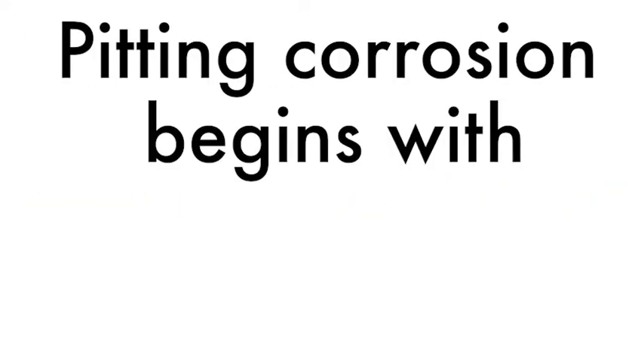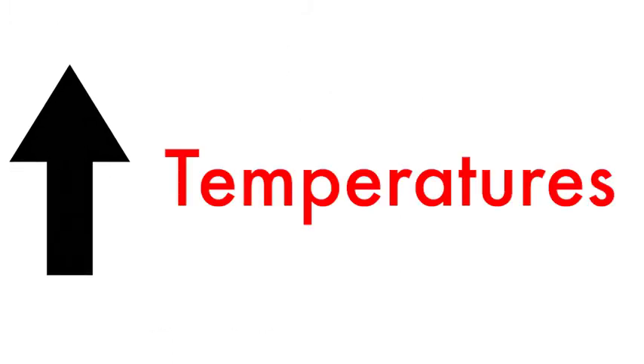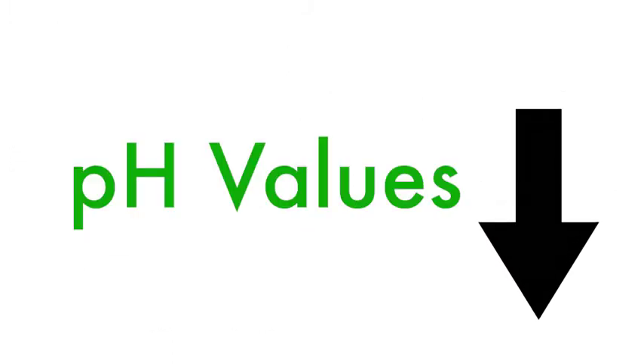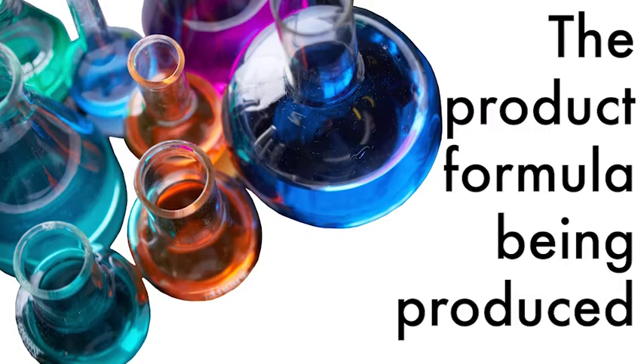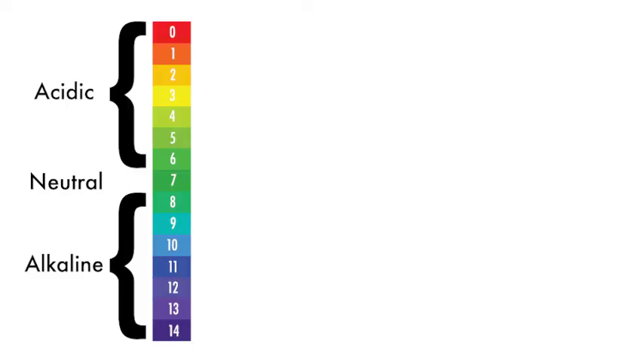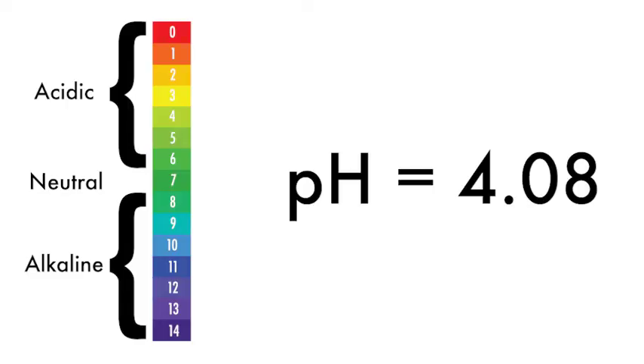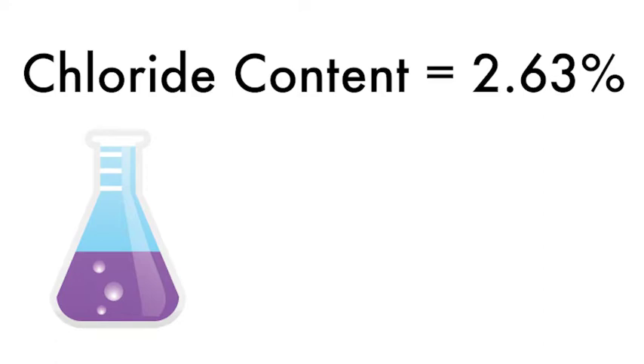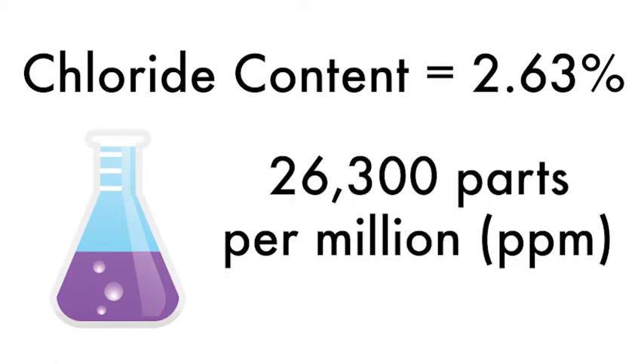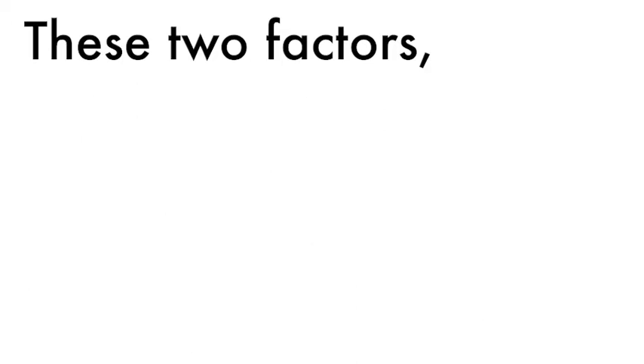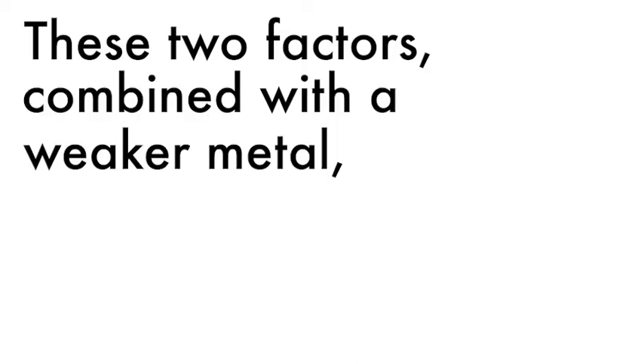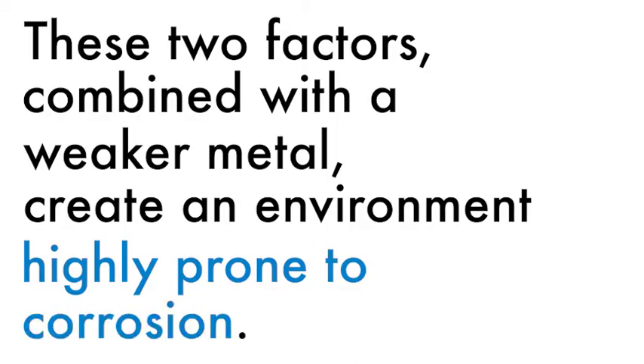Pitting corrosion begins with chlorides and accelerates at higher temperatures and lower pH values. The product formula being produced in the facility was found to have a pH value of 4.08 and a chloride content of 2.63%, or 26,300 parts per million. These two factors, combined with a weaker metal, create an environment highly prone to corrosion.